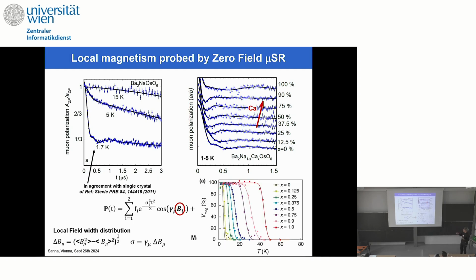Okay, but through μSR you can measure very nicely where the magnetic transition occurs. And so this is the sodium, then a little bit of calcium, a little bit more, until we get the full calcium sample. And this is the magnetic volume fraction, which is always 100%. It means that the samples are good. And the magnetic transition temperature increases as a function of calcium.